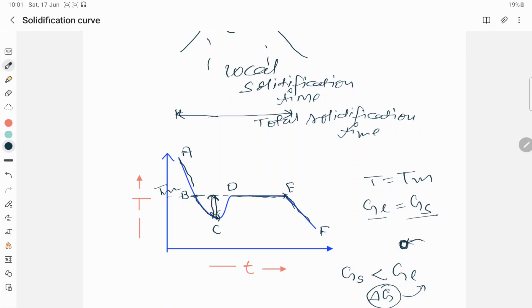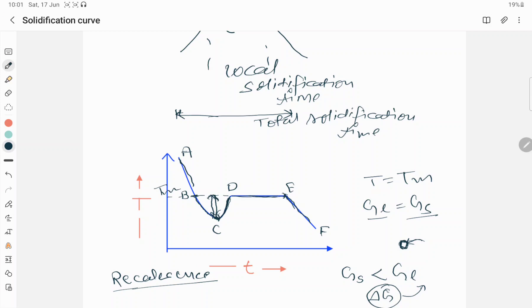The B-C region is the undercooling — I have discussed why undercooling is required. At point C, nucleation starts. C-D represents the latent heat of fusion, and when latent heat is released the temperature increases — this is known as recalescence. Recalescence is the increase in temperature of an undercooled liquid metal as a result of the liberation of heat during nucleation.